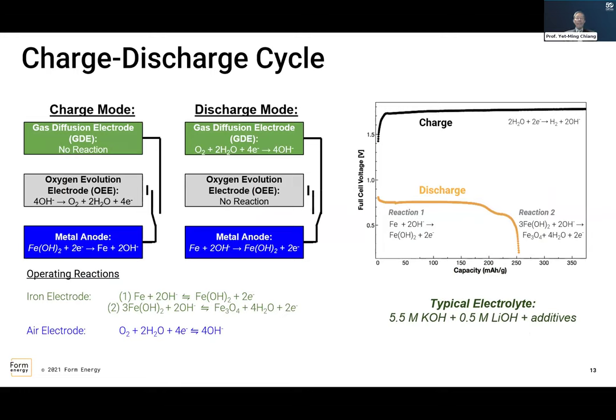It turns out that the design of this battery that Form Energy, the company that is developing this technology, has developed, has a couple of other interesting features about it. So I want to use this slide to explain two points. One is that in this case, there are actually two air electrodes. You have an iron anode, but you have to have two air electrodes. And one breathes in air, that's the gas diffusion electrode. The other breathes out air, that's the oxygen evolution electrode. Right? And this is done for a number of technical reasons that I won't go into right now. Right? So this is the actual design of the iron air battery.